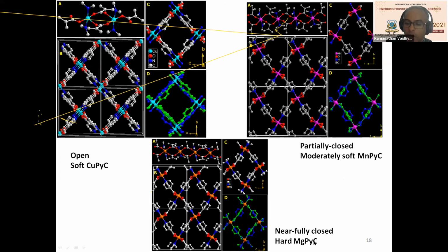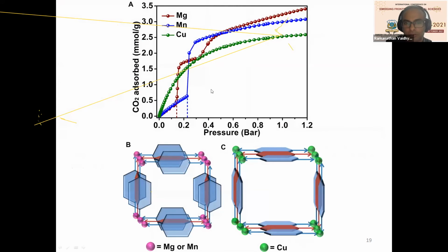We are showing how the softness-hardness mismatch can introduce a degree of freedom for the rotation, and how the gas pressure can exploit that. So here is the adsorption isotherm experimentally measured for the copper, manganese, and magnesium. You can see that the gating pressure, at the same temperature, is a particular pressure for the magnesium, the brown color. It is somewhere around 0.16 bar.